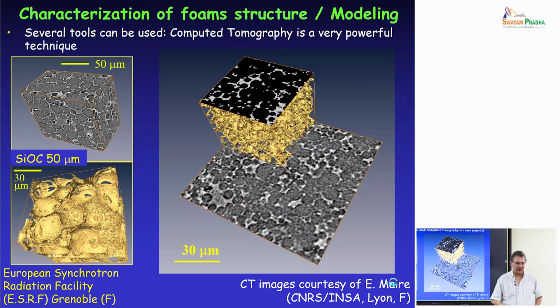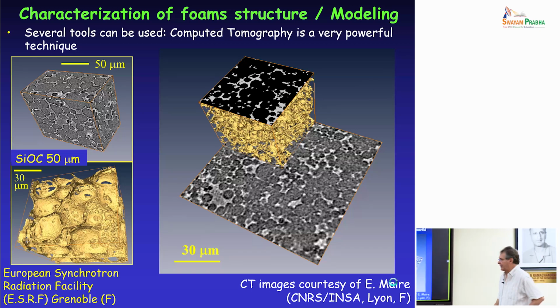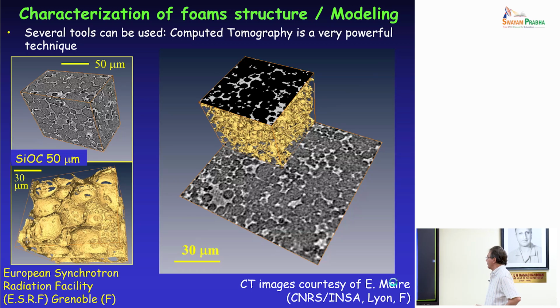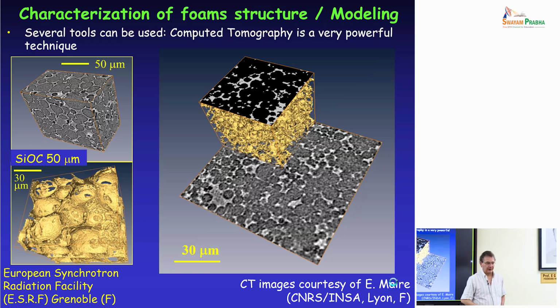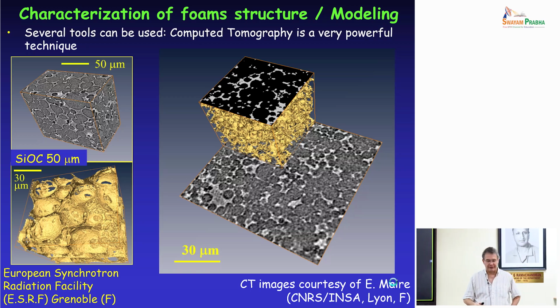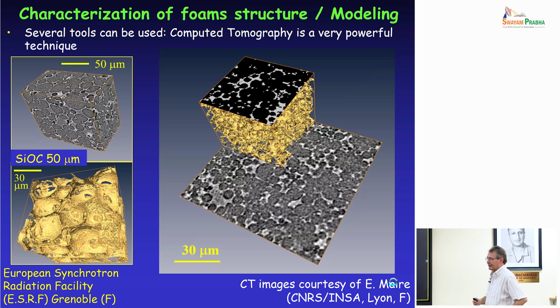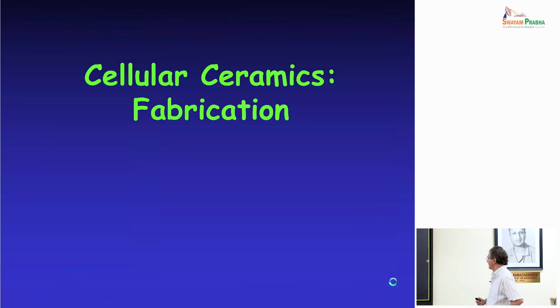So when you do characterization of the foams, as I said, you can use computed tomography. This is actually synchrotron radiation, because you can see the resolution is much higher than conventional, at least in those days, computed tomography. Now the resolution is about 3 microns for desktop tomography equipment, but with this synchrotron radiation, you can go below 1 micron in terms of resolution.